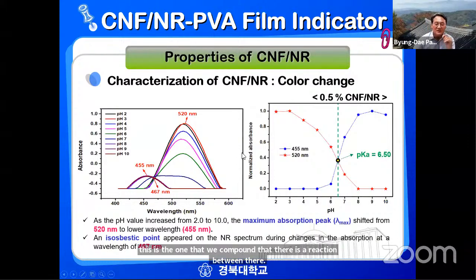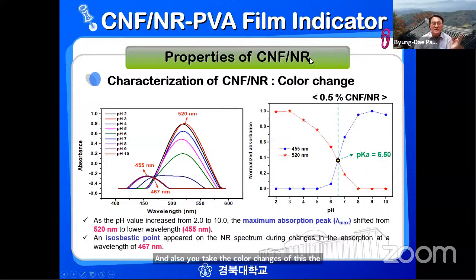And also we check the color changes of this composite material, CNF with neutral red. Here the isosbestic point is about 467 nanometers, and they also have absorption like this. The pKa is not much different, pretty much the same as neutral red. And actually this one contains 0.5% CNF neutral red composite material in the matrix.